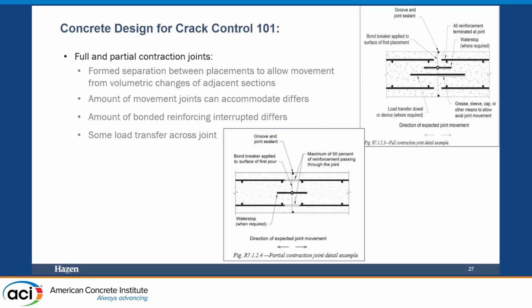to happen. Partial contraction joints, there is some reinforcing that crosses, up to 50% is what we would consider as a partial contraction joint for 350. And water stops are shown in these walls, again, because these were developed for 350 type structures.